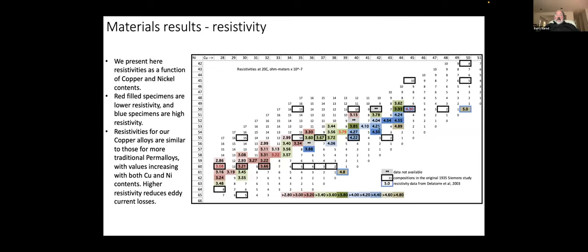We ended up wanting to have lower saturation moment. We want to have higher resistivities, which can be achieved with the higher copper contents. In fact, these numbers are similar to the resistivities that you'll find in the typical commercial permalloys, the molypermalloys, which have a range of 4 to 5 to 6 times 10^-7 ohm-meters. So very comparable on resistivity, in areas which we are ultimately going to find fairly interesting.